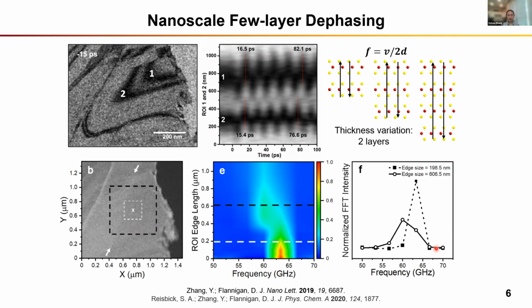And when the ROI edge length increases to include regions of both thicknesses, we can then see a gradual shift of the frequency to 60 gigahertz. And also we can see this widening of the FFT peak. And the subtle effect can only really be seen because of the nanoscale probe of UEM.